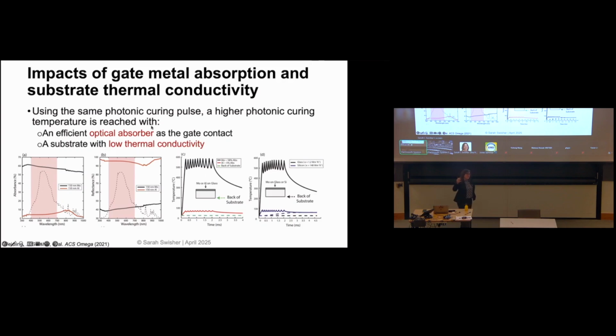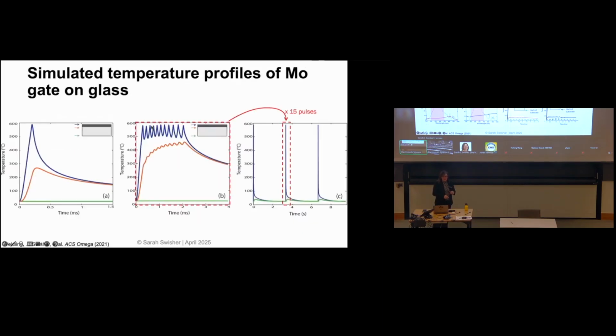Because that optical energy is now getting sucked into the silicon. Silicon is a great thermal conductor. So it sucks away the heat, and it doesn't stay up at the top. So for the same amount of energy that you deposit, you're spreading that energy out. It doesn't get stuck at the top, so you can't heat it up as much. Okay? So this is all about engineering the materials in the stacks so that you keep the heat where you want it. That's how photonic curing works.